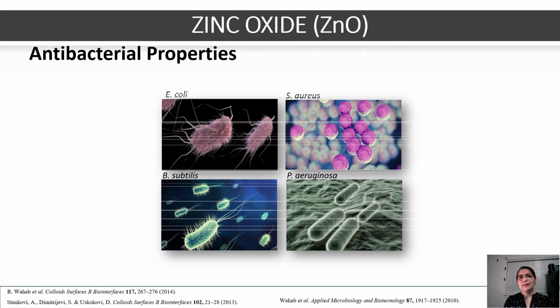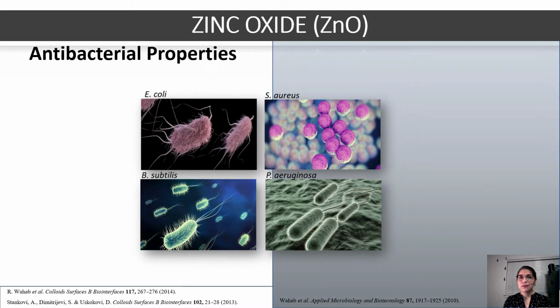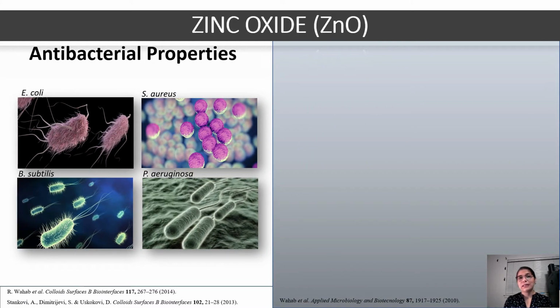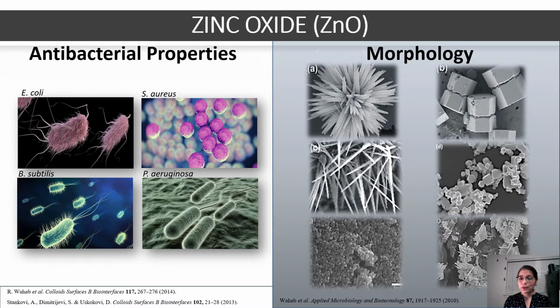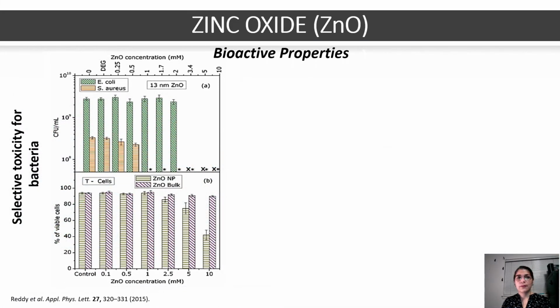On the other hand, zinc oxide is an inorganic material with proven antibacterial properties against different pathogens. It has become a viable alternative for the development of antibacterial materials, mainly due to its low cost of production and easy control of morphology. It is important to know that both morphology and particle size play an important role in the antimicrobial activities of zinc oxide. In this sense, a good antibacterial performance has been reported for spherical morphology and nanometric dimension. Regarding the zinc oxide bioactive properties, it has been reported that zinc oxide has a selective toxicity for bacteria with a minimal effect on human cells.